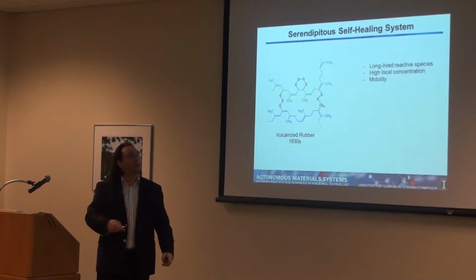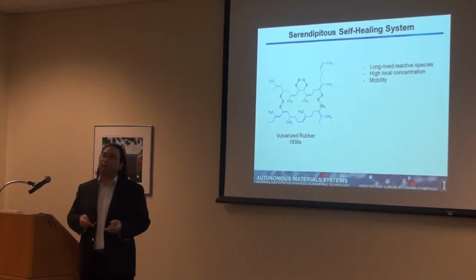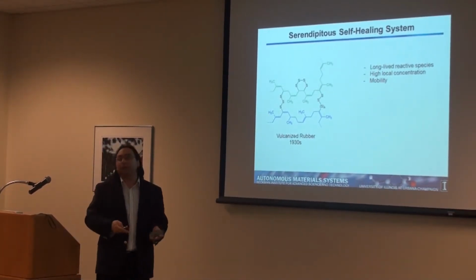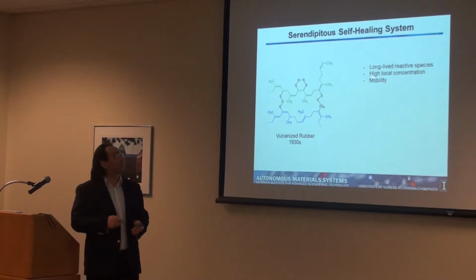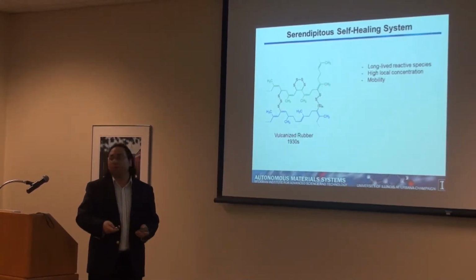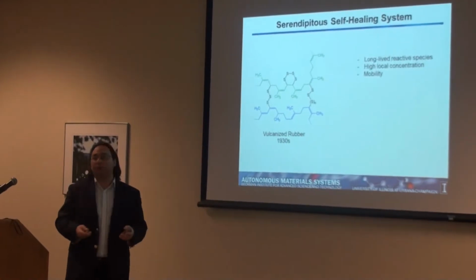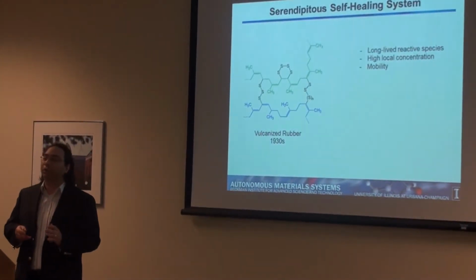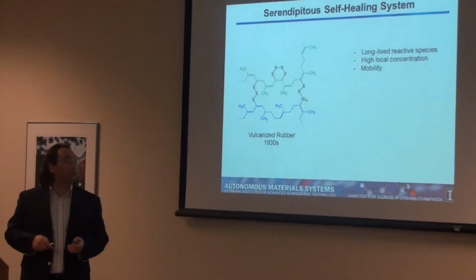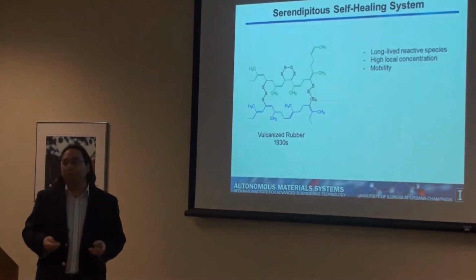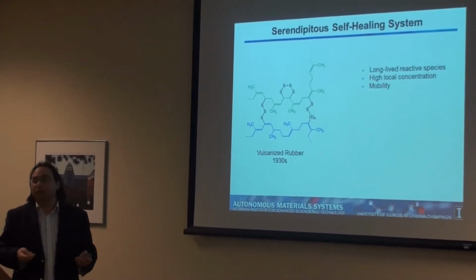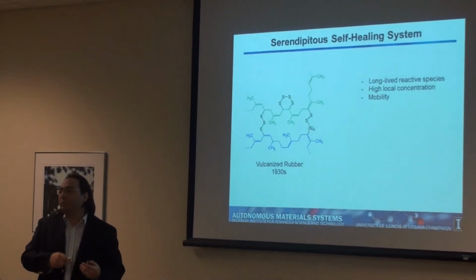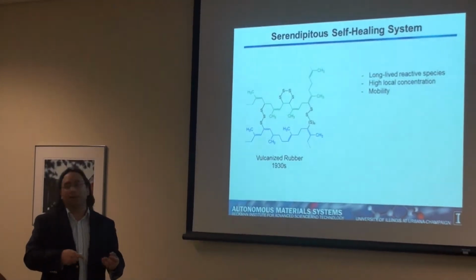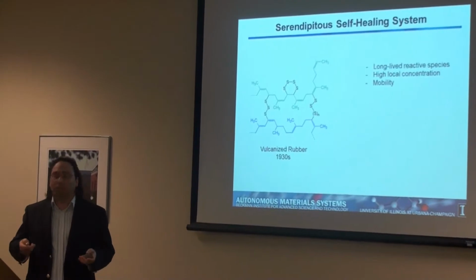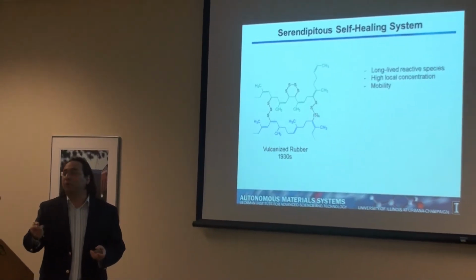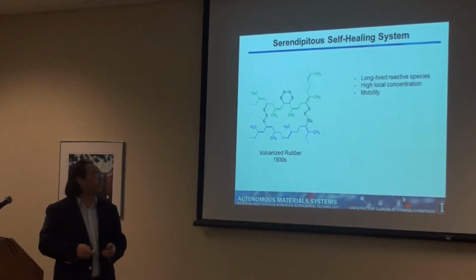In this case, sulfur radicals are quite long-lived as long as they don't have oxygen. They have to be at high local concentrations. In this case, the concentrations are between 5 and 20%, depending on the rubber. And there is the question of mobility. Rubbers are soft systems, so there is some mobility to the chains, so they can actually get to the other reagent and make a new bond.